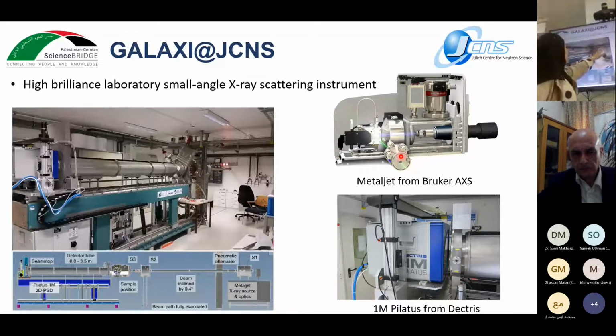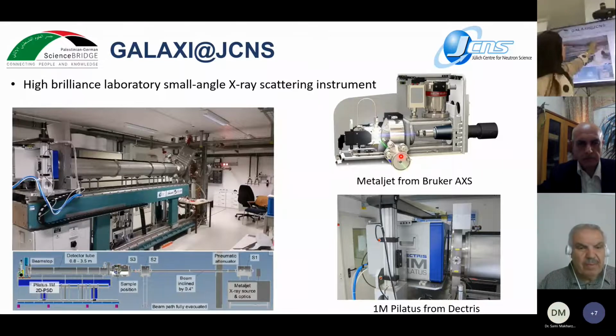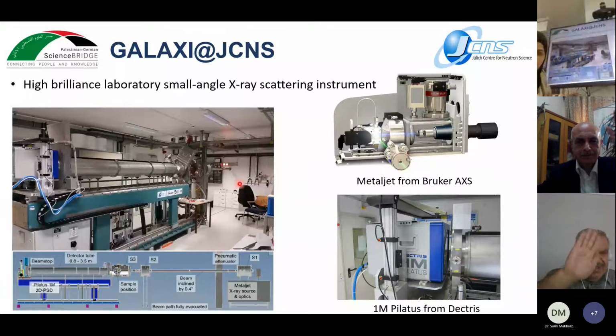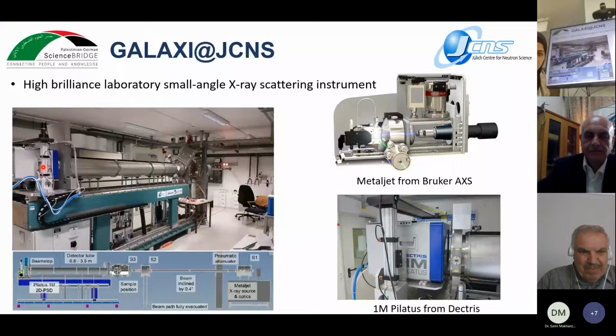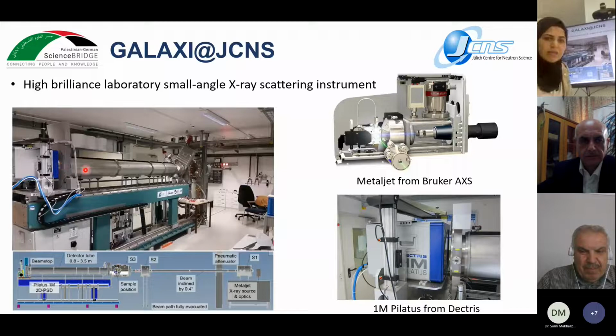Then for the X-rays, we have parabolic optics in this room where the X-ray source is located, and the beam goes through this evacuated tube until it comes here to the sample chamber. Here we locate our sample, and there are evacuated tubes all the way up to the detector. We have a PILATUS detector. The Q range that we can obtain depends on the sample-detector distance, which we can control through this tube in five steps. The detector distance can be varied from 0.8 up to 3.5 meters.